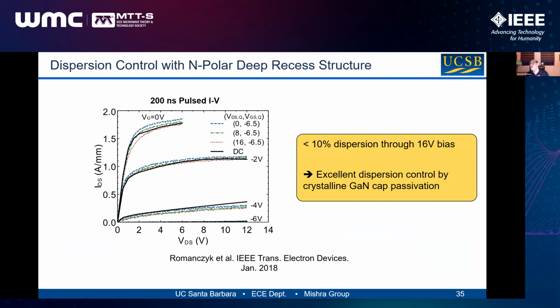And you get no dispersion with no passivation. Why? Because the GaN cap itself is the passivation. And you get beautiful looking curves, high current, and low dispersion. Romanczyk showed this.